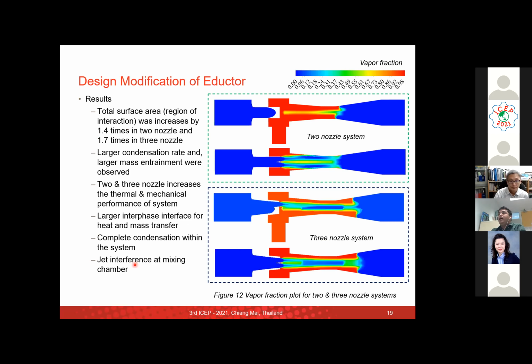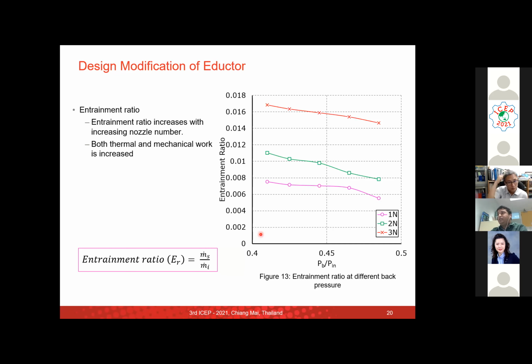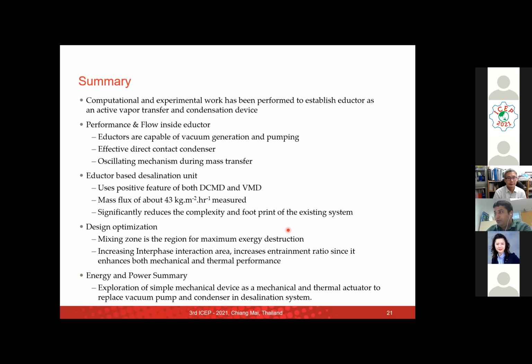And this is the computational result we see, where there is larger mass transfer happening in the system. This in turn also increased the thermal performance of these eductors. And we can see here, the 3 nozzles has a significantly larger entrainment ratio compared to the 1 and 2 nozzle systems. So this also shows that there is more potential for higher performance of the system in desalination units.